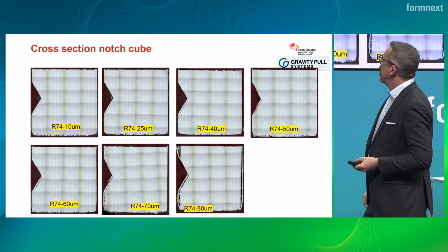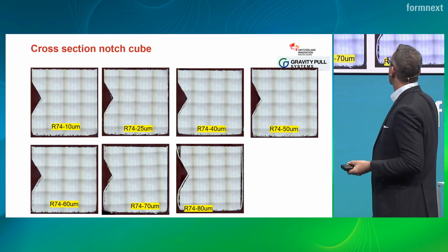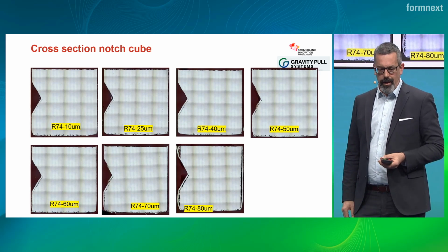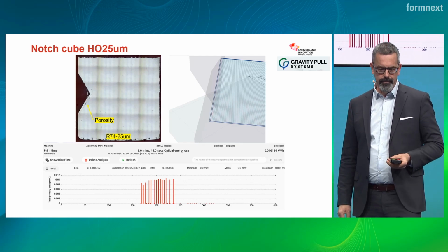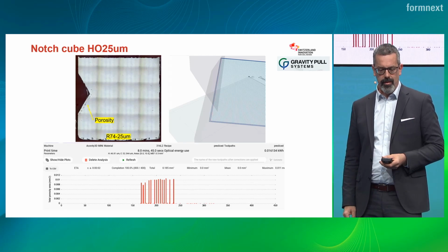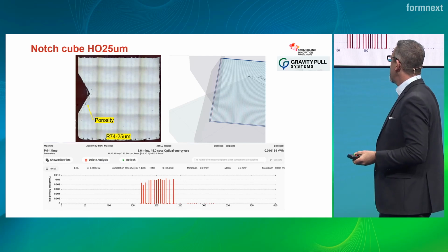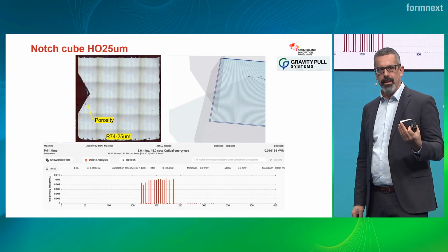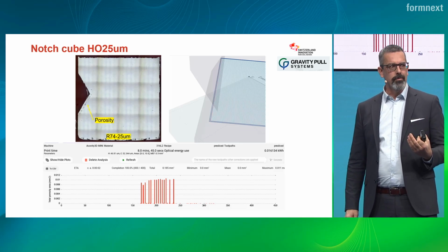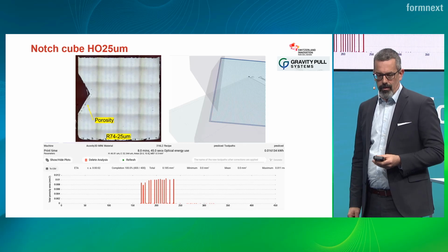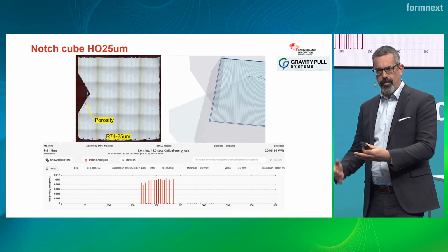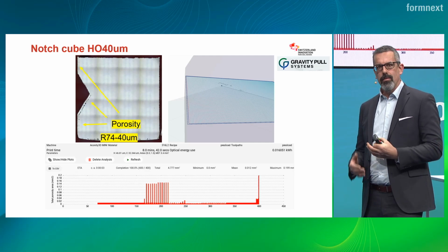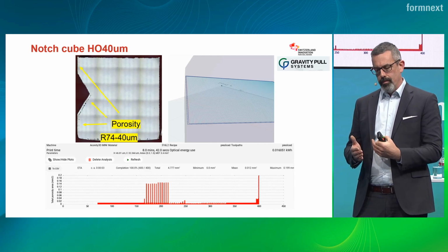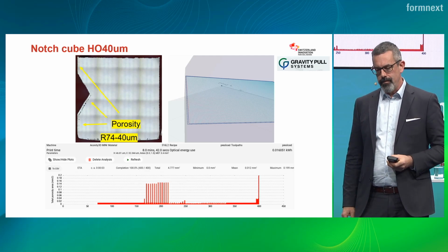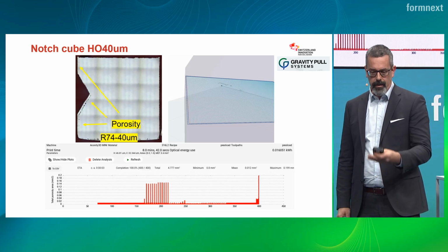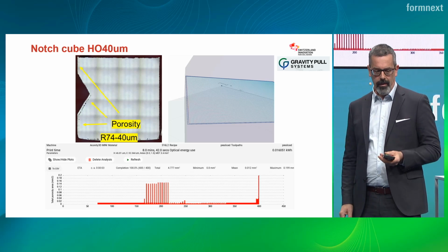And you see that in the down-facing part, you never find porosities, but in the up-facing part, yes. And in some, you see it in the vertical as well. PAM now predicts this. You see, there is a graph that shows the total porosity area detected or predicted from the digital file. It's not from the build job, it's predicted from the digital data. You see that this is correctly predicted for 25 micron hatch offset. Here we switch to 40 micron hatch offset, and it also predicts some porosity in the vertical. You can also see it in the sketch of the toolpath data.